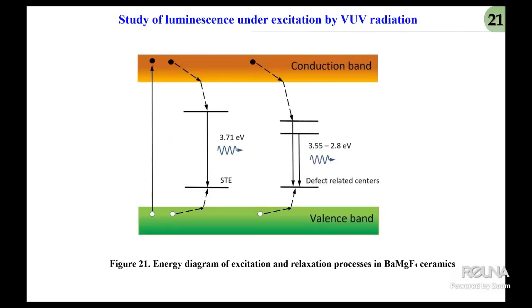This slide presents the energy diagram of excitation and relaxation processes in BaMgF4 ceramics under vacuum ultraviolet excitation. Under VUV excitation, electrons are promoted from the valence band to the conduction band, after which the energy relaxes through several competing channels. The first pathway is associated with the formation of self-trapped excitons. The radiative relaxation leads to photon emission with an energy of approximately